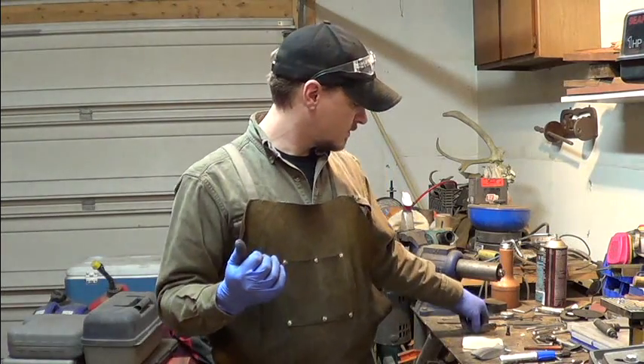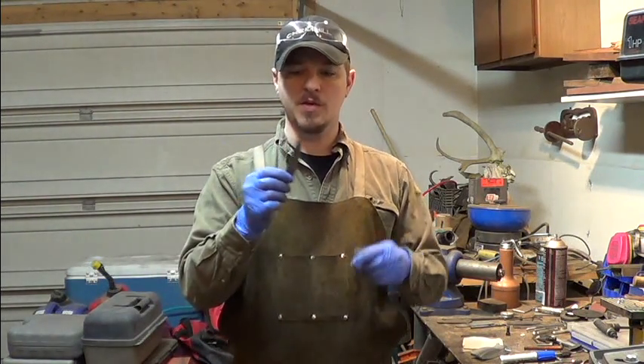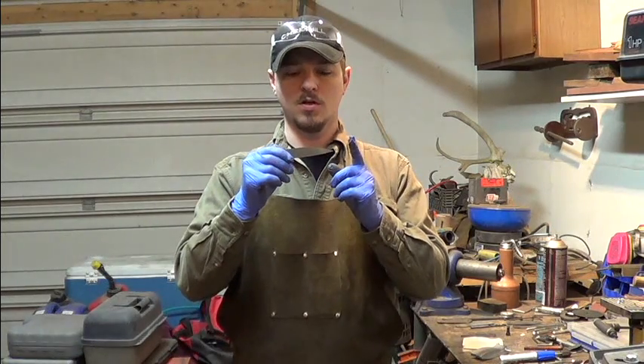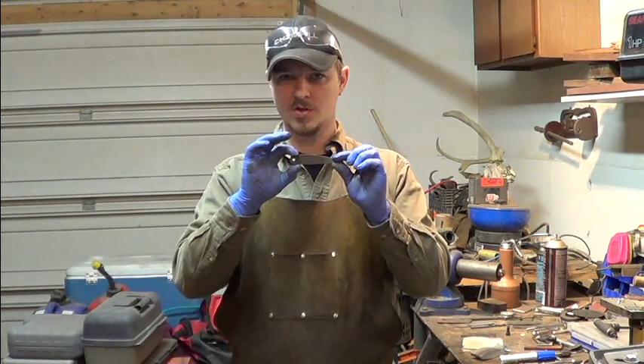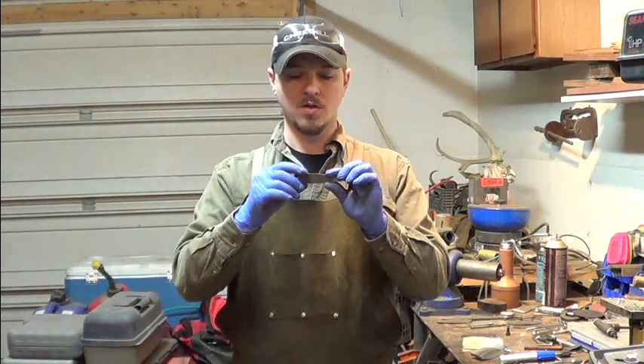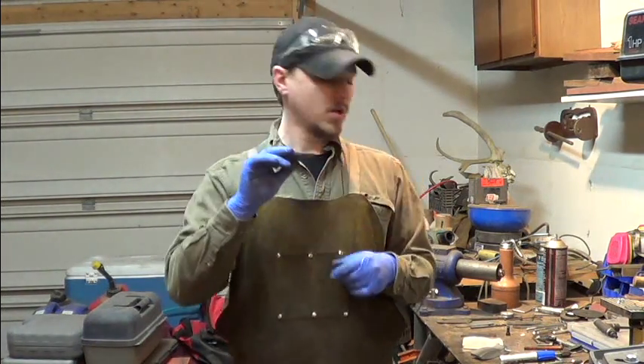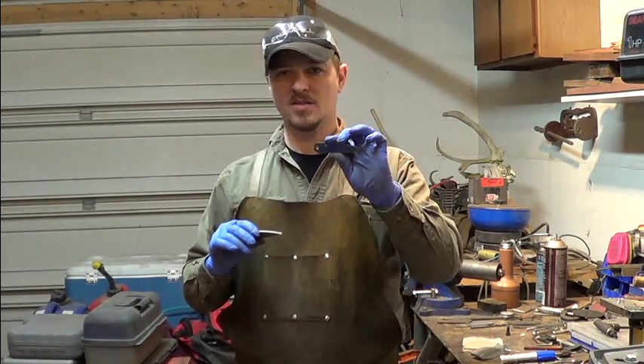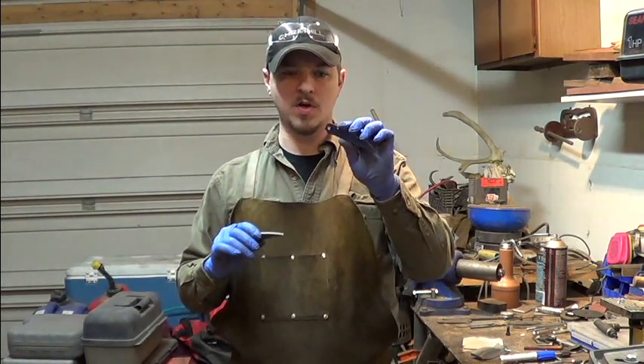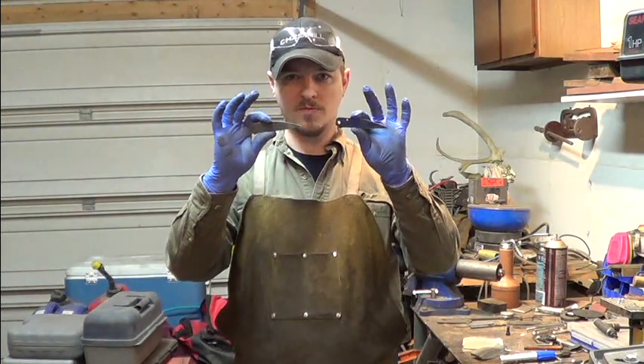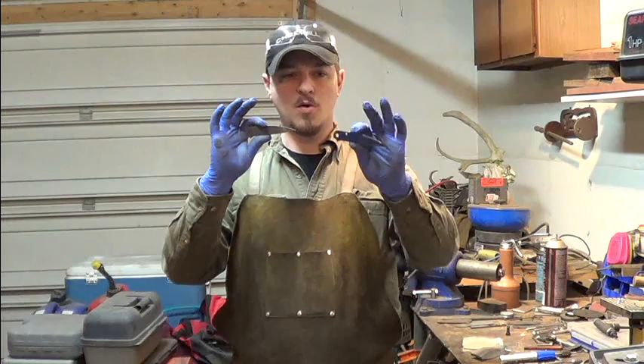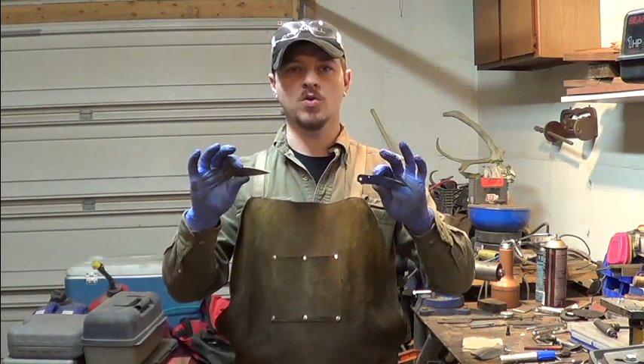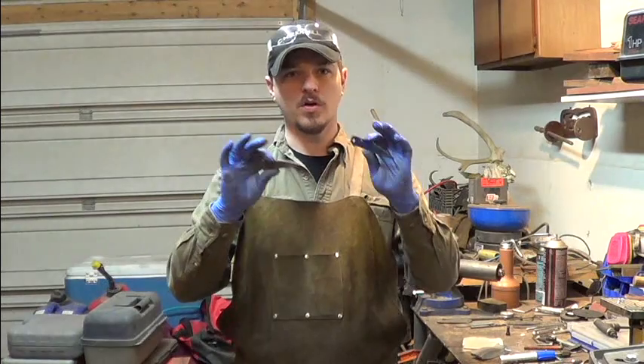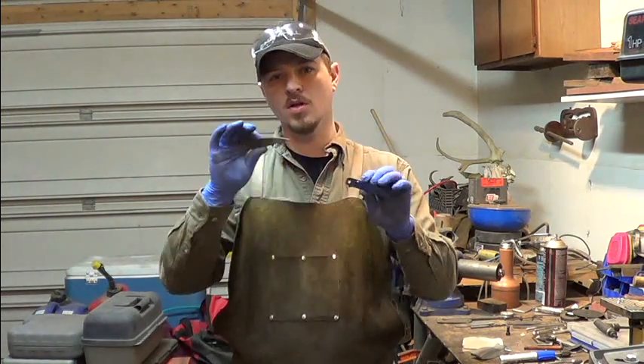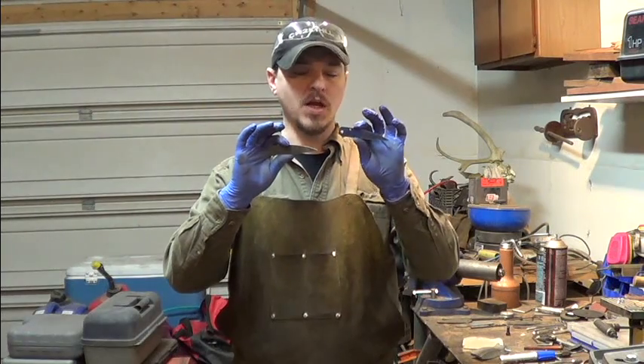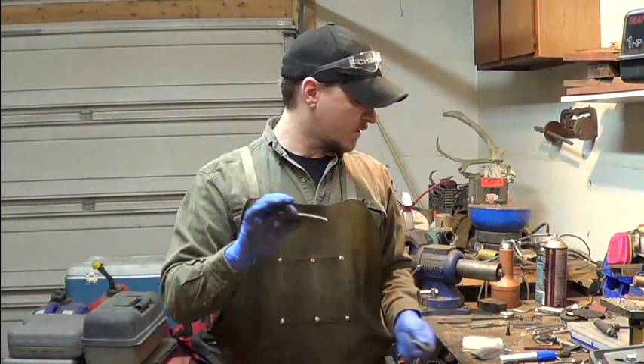The stainless, this CPM S30V needs 2 cycles of 2 hours each at 400 degrees in the oven with air cool in between. So this will go in with my Damascus, because this also gets 400 degrees for 2 hours. So the first cycle, all 4 knives are going to be in there, and then I'll pull out all 4 knives, let them air cool with the oven still on, so I don't lose my heat. It only takes about 5 minutes to air cool. I'll set them by the sink or whatever, and then I'll be ready to rock and roll with these.